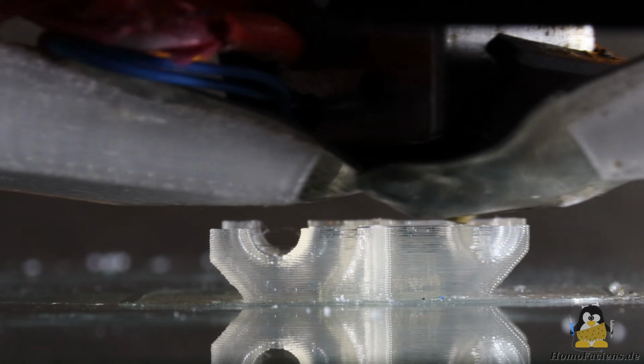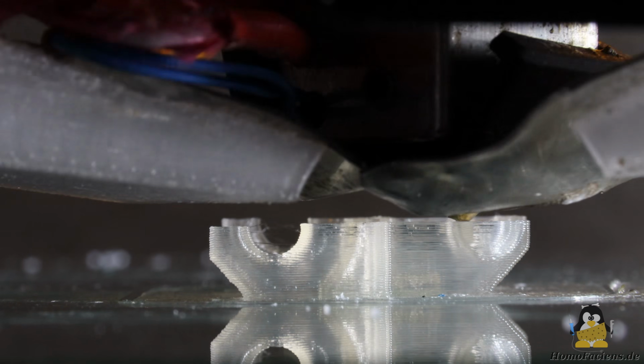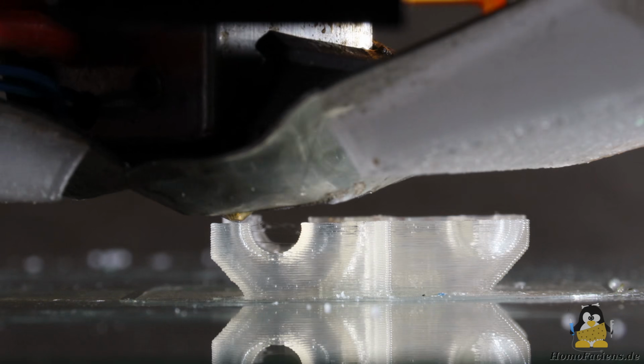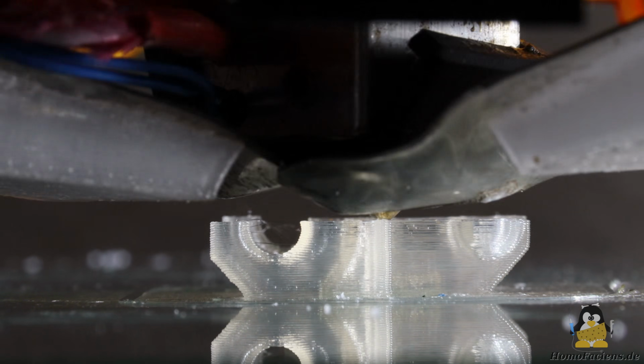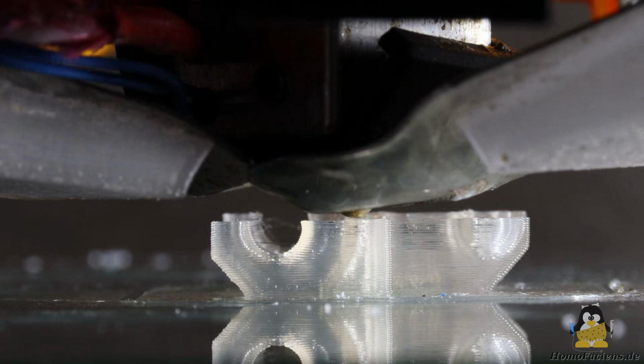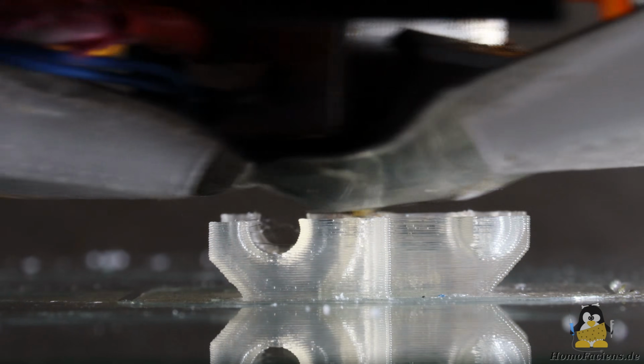Now let's look at the industrial powder. It is printed using the same parameters, with the only change being the filament factor. This had to be set to 140% relative to the recycled powder. Based on the difference in density, a value of only 108% would have been expected. Obviously the distinct flow behavior of the very fine grains makes the difference. The gap between the screw and the extruder wall is necessary to allow the air trapped in the powder to escape upwards. If this gap is too wide and the material being processed is very fine grained, slippage occurs between the screw and the extruder wall as the powder is pressed down.